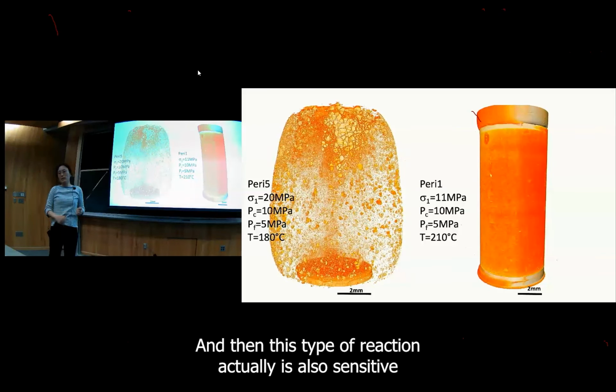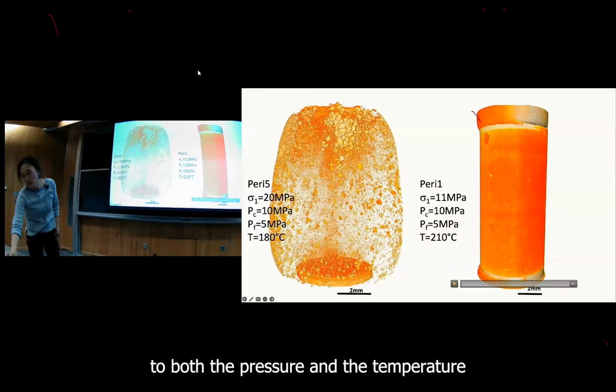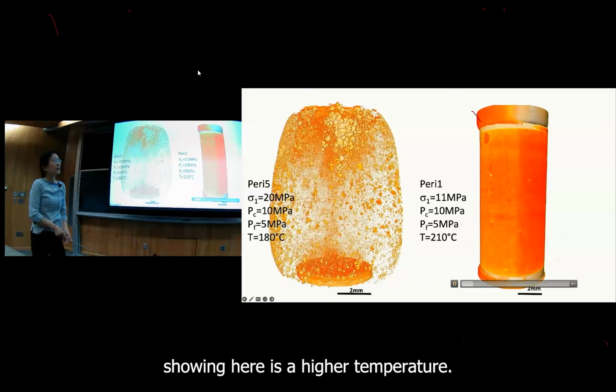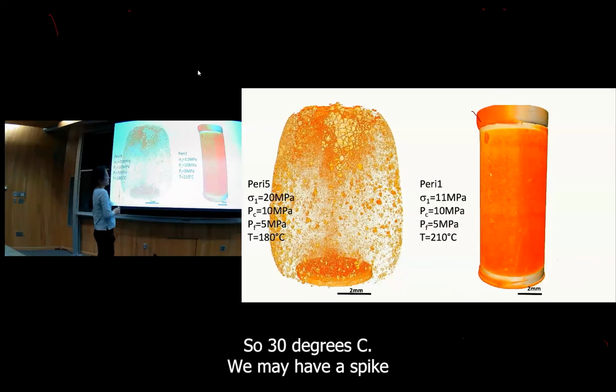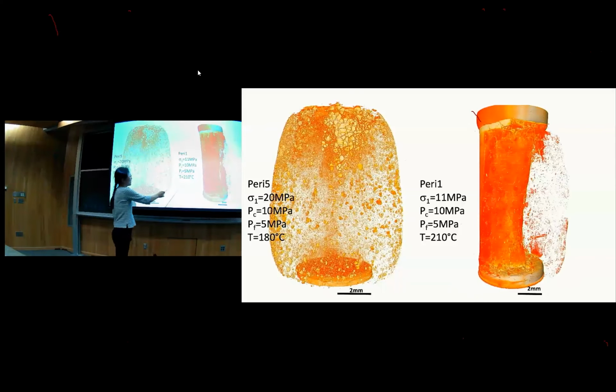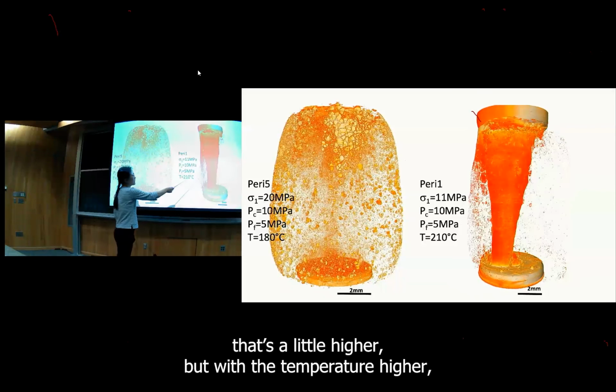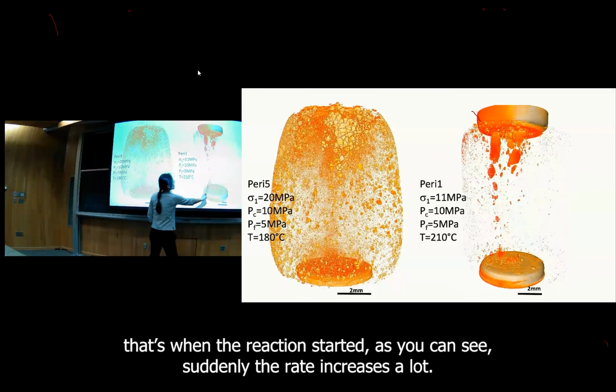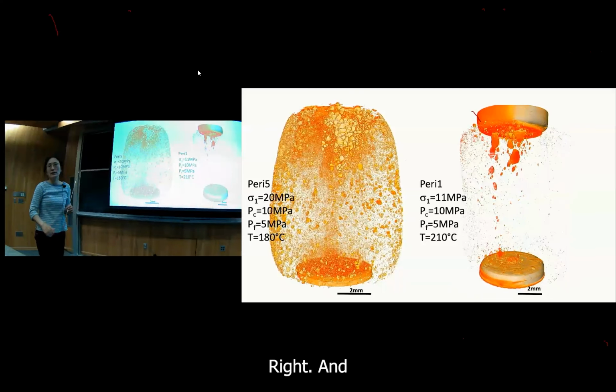And this type of reaction is also sensitive to both pressure and temperature. Showing here is a higher temperature. It's 30 degrees C, and we may have a spike that gets a little higher, but with the higher temperature, when the reaction started, you can see the rate suddenly increases a lot, all right?